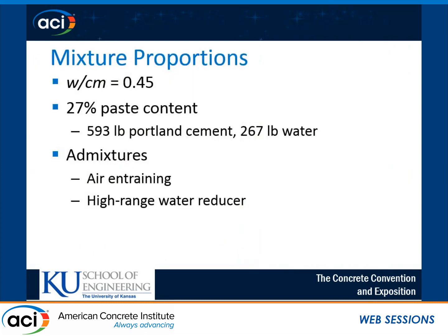The mixture proportions that we use in our study, for each of these series, that we kept constant are a 0.45 water to cementitious materials ratio. We use 27% paste content, and for our 100% Portland mixes, which is our control series, that converts to 593 pounds of cement and 267 pounds of water. And to get our air correct, we use an air entraining admixture, and to vary the slump, we use a superplasticizer.